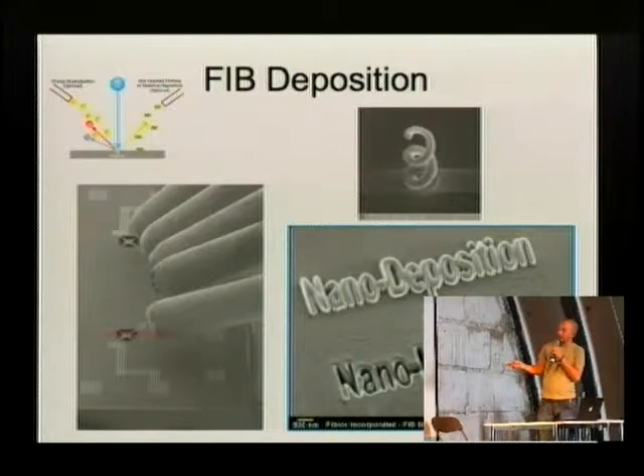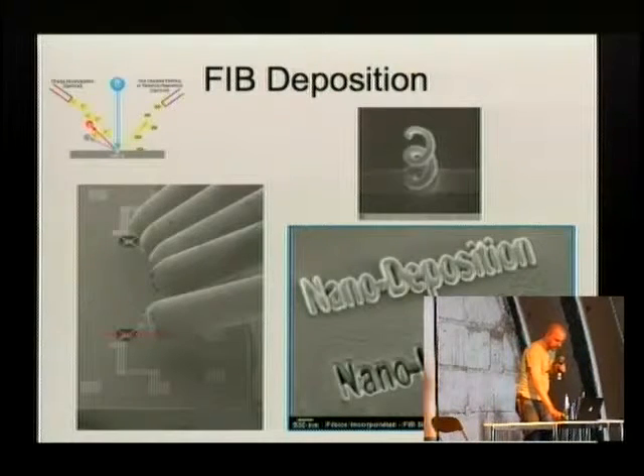Here we see an example where, on the one side, you have the substrate milled away, and on the upper side there was some insulator deposited onto the substrate by this technique. And if you do it carefully, you can even create 3-dimensional shapes.